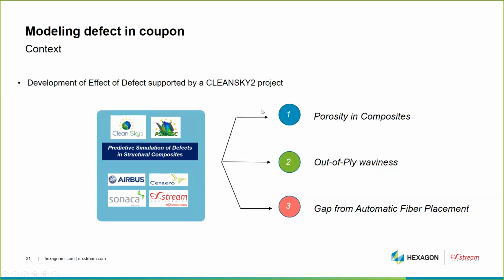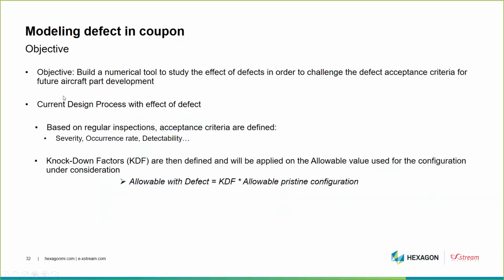So in this project, we are dealing with three types of defect. The first one is the porosity in the composite. The second one is the out-of-ply waviness, and the third one is the gap from automatic fiber placement. The reason why we wanted to focus on the effect of the defect is because we had the objective at the origin to build a numerical tool to study the effect of defect in order to challenge the defect acceptance criteria for future aircraft part development.